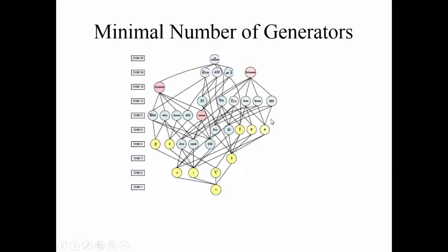In this group, I've put the minimum number of generators. So here, all on the bottom, you can see the 1 and 1 bar, 2 and m, 3 and 3 bar, 4 and 4 bar, and 6 and 6 bar, giving us the cyclic groups. And then the ones with three generators are 4 over mm and 6 over mm, and then the rest of them all have two generators. This is mathematically very important, and you can pursue this at another time.